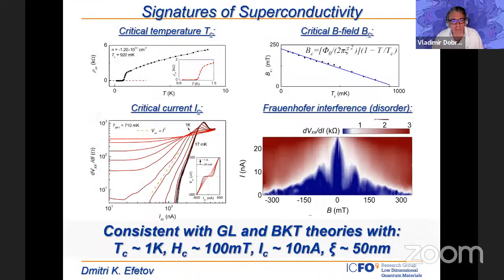Yeah. So I think this curve basically demonstrates it a little bit. I think what you're referring to is that above the superconducting transition, the temperature dependence is more or less linear, right? There were initial comparisons. Some people were really trying to draw direct analogies to the cuprates. Looking at this linear temperature dependence could remind you of a strange metal phase, like the one observed in the cuprates. But then other groups were also explaining these results just by electron-phonon interaction.